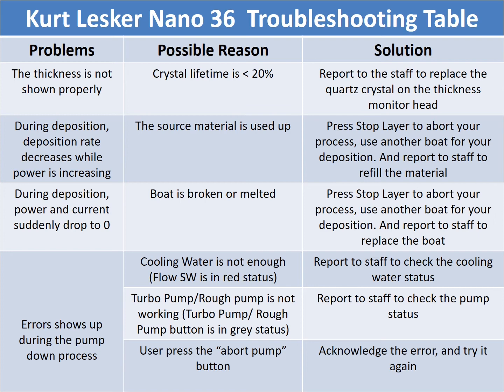And if you find that during deposition your power, your current, suddenly drops to 0, it may be because your boat is broken or melted during your deposition process. Press stop layer to stop your process. Use another boat for your deposition and report to the staff to replace the boat later.